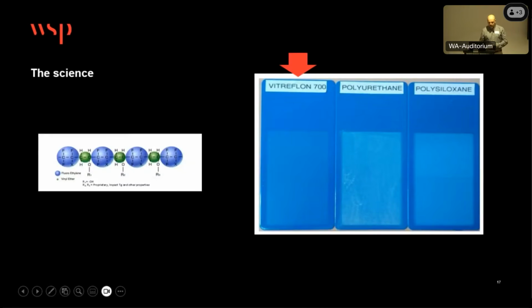So the science, and Michael will provide a whole lot more detail on some of this in his presentation, but it was my curiosity that drove me to ask, okay, what is the reason behind why these fluoropolymers perform so much better than other coatings? Because I needed to be confident that the solution I was putting forward to our client was going to meet their requirements. So I did a little bit of digging and found that these coatings are really resistant to UV degradation because of the fundamental chemistry of the fluoroethylene vinyl ether, which forms the backbone of the resin in a fluoropolymer coating. And it turns out that the bond energy of the fluoroethylene significantly exceeds that of the energy of the incoming UV light, and because of the concentration of the resin within the coating, it demonstrates superior UV resistance.